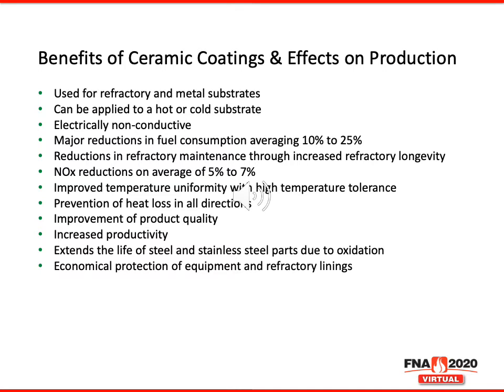Let's take a look at some of the benefits of ceramic coatings and their effects on production. These coatings can be used for all refractory and all metal substrates. They can be applied to a hot or a cold substrate. They are electrically non-conductive, so the welding of metallic anchors or the repair of a steel shell of a furnace must be done prior to any application of a coating.